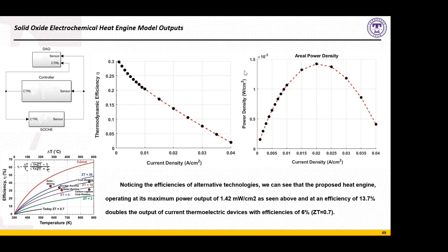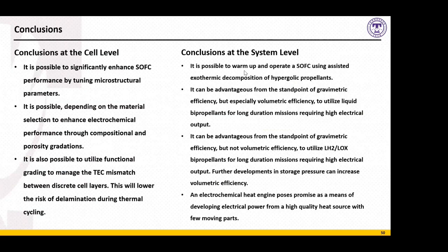Now, our conclusions. The conclusions at the cell level, again, as we saw, it is possible to significantly enhance the SOFC performance by tuning the microstructural parameters of the SOFC. It is also possible, depending on the material selection, to enhance the electrochemical performance through compositional and porosity gradations that are implemented through the 3D printing method. It is also possible to utilize functional grading to manage the thermal expansion coefficient mismatch between discrete cell layers.